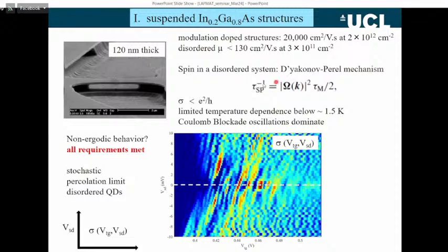If we have a disordered system, the spin properties are determined by the Dyakonov-Perel spin scattering mechanism. So if we have this mechanism operating in a disordered system, the spin scattering rate is very low. The spin scattering rate, 1 over tau, is determined by the Rashba spin orbit coupling effect, and tau_m, the elastic mean free scattering time, which can be very low in these disordered systems. This time is very low, which means we get a very, very low spin scattering rate. So electron spin in these systems must be much more visible because it's got a strong spin lifetime. So that was the idea with this system.